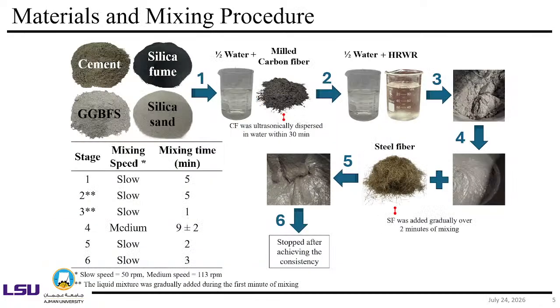So here is the mixing procedure. I want you to notice that. Instead of pure cement, which is very high in carbon footprint, we also mix in GGBS and silica fume. And we also use something called PLC, which is limestone based. For those who are not familiar with concrete, those are all much lower in carbon footprint than traditional cement. GGBS is tens of times lower in carbon footprint. For limestone, that could be hundreds of times lower. So even if you include just 10% or 15%, that's a huge change in terms of carbon footprint reduction.